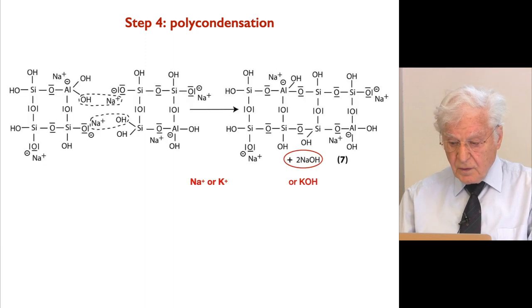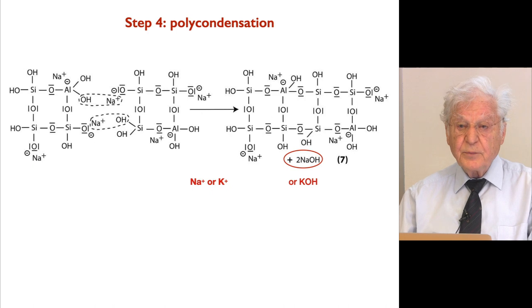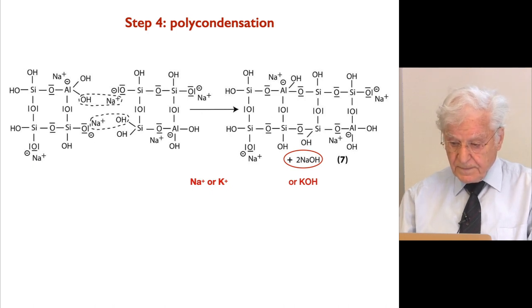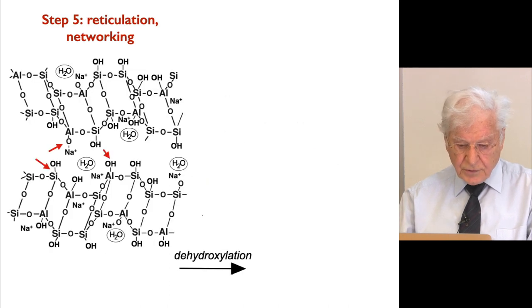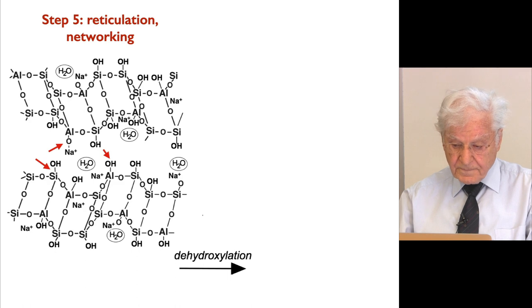Let's look at step number four, polycondensation. On step number four, we have squared oligomers that result from the depolymerization of the silico-aluminate that we are using, which will polycondense, polymerize each other, and build a two-dimensional chain that polycondenses into a 3D network. With time, this is in step number five, the side groups, SiOH, react with the opposite Al-ONa and AlOH. During the reaction, water is expelled from the structure,